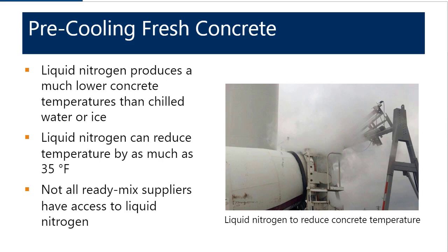So for larger projects, the contractor may be able to set up its own liquid nitrogen station. But a lot of times, if there's not enough mass elements, the costs for the setup aren't able to be justified. But the nice thing about it is if it's available in a given market, liquid nitrogen can reduce temperatures by as much as 35 degrees, and in some cases a lot more, depending upon what the initial starting temperature is.